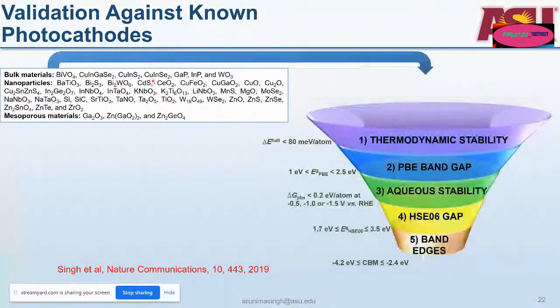And we took all the photocathodes which were known to us at the time we did this study. And you might recall this list from the first few slides, where we have all the bulk photocathodes, the nanoparticles, and the mesoporous photocathodes listed over here. And we fed it into the screening funnel which we have designed to see what emerges out of it. Do we get any of these candidates out of it? And if we do, what is their specific strength?